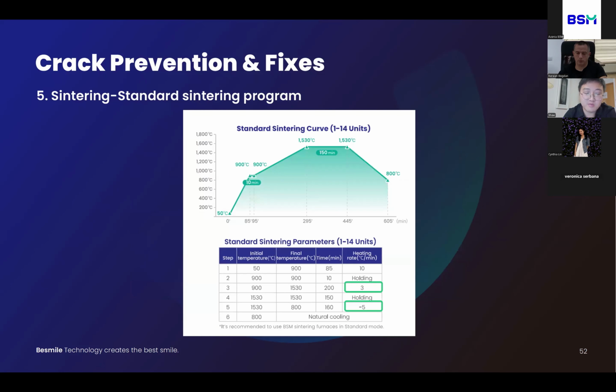And as for the sintering process, we should use the standard sintering curve from the manufacturer. The most important is the heating rate or cooling rate. You can see that in the standard sintering program of our 3D Master, the heating rate is like 3 degrees per minute, and the cooling rate is 5. If the heating rate and or cooling rate is too big, there's a risk of crack or deformation during sintering.